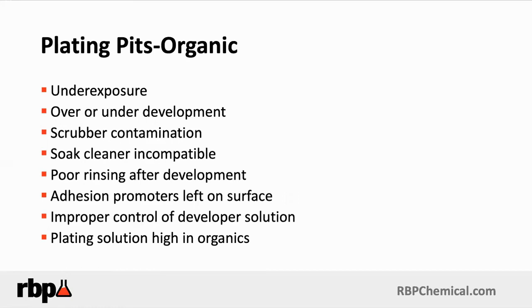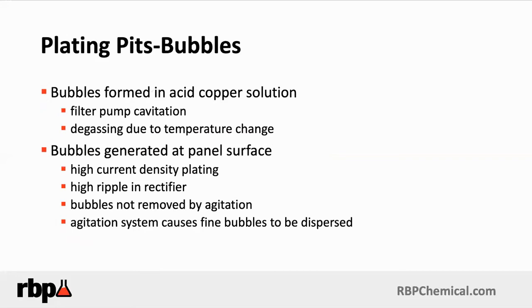As troubleshooters, you must first understand: are the plating pits organic or inorganic in nature? Organic pits come from things like photoresist residues, fingerprints, other surface contaminations, adhesion promoters left on the surface from the photoresist, or incomplete developing or rinsing. The other situation relates to inorganic pits — what I would call air bubble or gas bubble entrapment — which can also lead to pits. Bubbles or gas bubbles are a completely different mechanism and troubleshooting situation than an organic type of pit, so make sure you distinguish between pits caused by air bubbles or hydrogen gas versus organic causes.